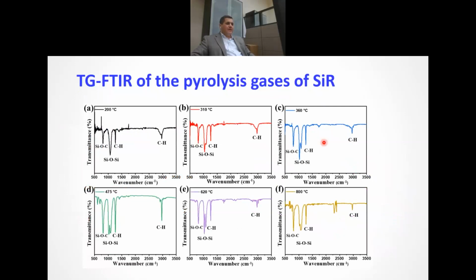Yeah, and we confirmed this through the TGA evolved gas analysis, analyzing the gases that form due to the degradation in situ. Here in CAM, we have the TGA that is attached to the FTIR, and we analyze at different temperatures what happens. With the intensity of these different peaks, we decided that for the low molecular weight ones, we have more silicon oxycarbide or silicon carbide. This is based on intensity. It doesn't clearly show in this one, but if you compare the intensities, you will be able to get this point. And actually, this is for one sample only, sorry, it's not comparing the different samples. It's just to show you what we do exactly. You take a sample of the evolved gas and you do FTIR at different temperatures. The machine does this for you, and we have this capability here in CAM.